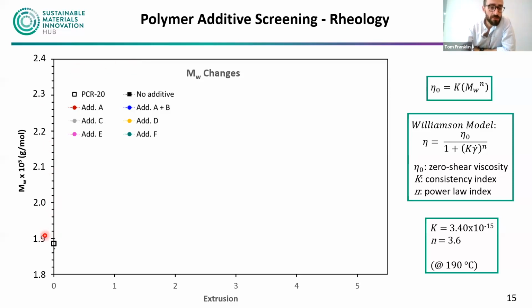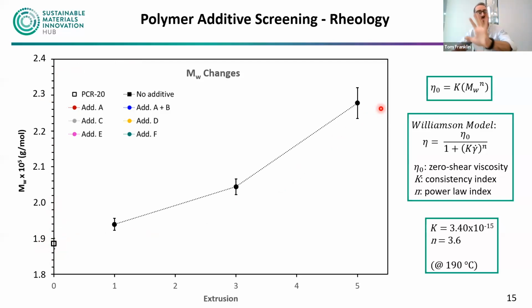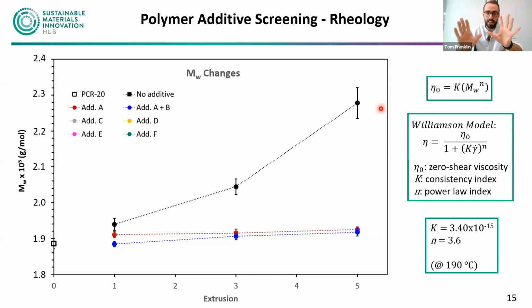So if we just take our resin as it is with no extrusion, we have a molecular weight down here. And if we extrude with no additive, you can see we have a very clear increase in molecular weight as the number of recycling steps increases. So that's with no additive. Both of our antioxidants perform perfectly as expected, nice and flat, very little change in molecular weight. That's what we would expect. So it's arresting that degradation, even in this first and initial step.